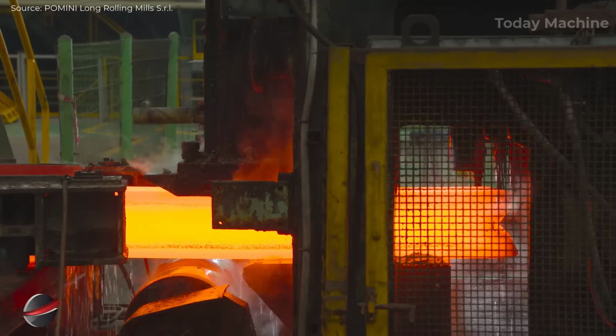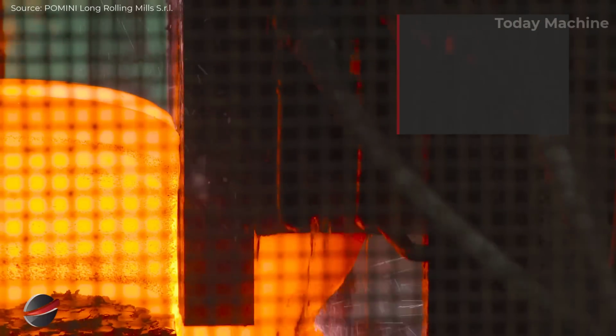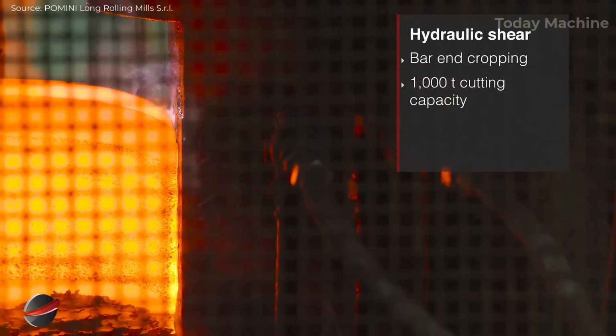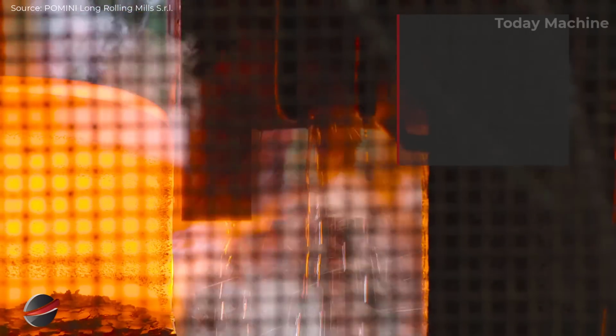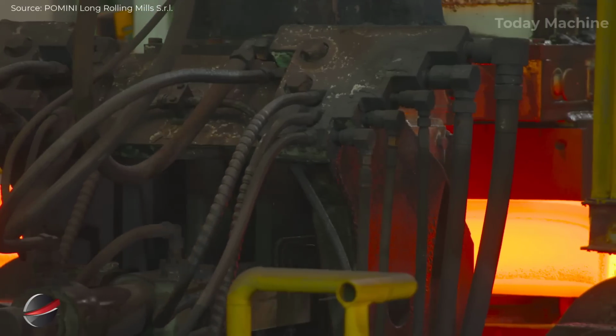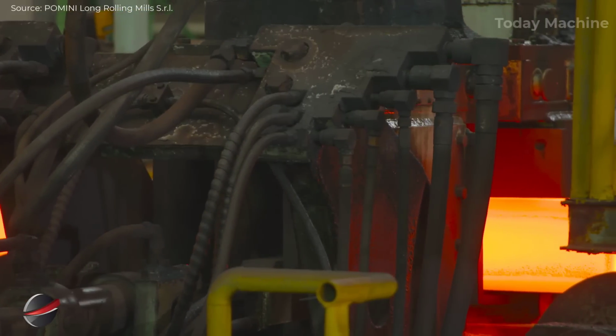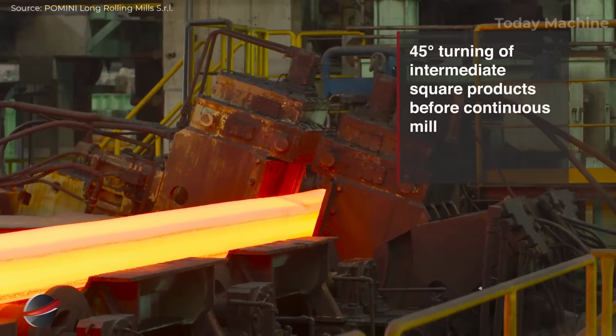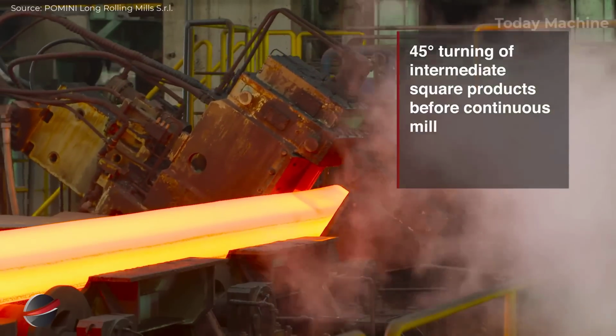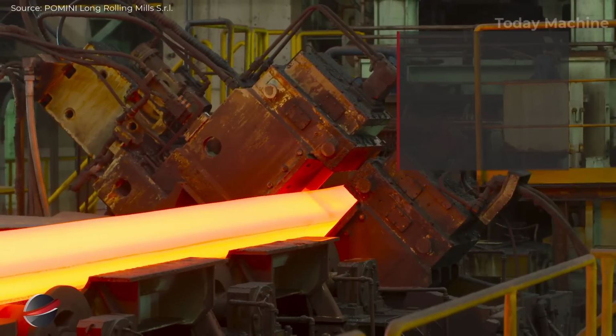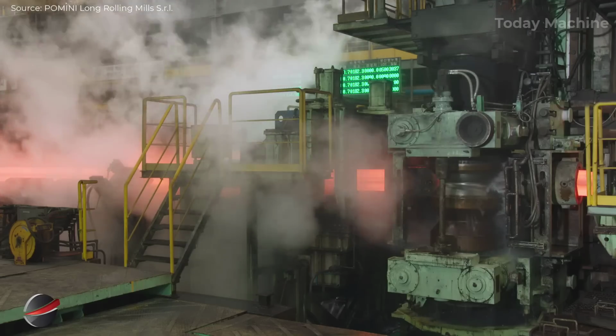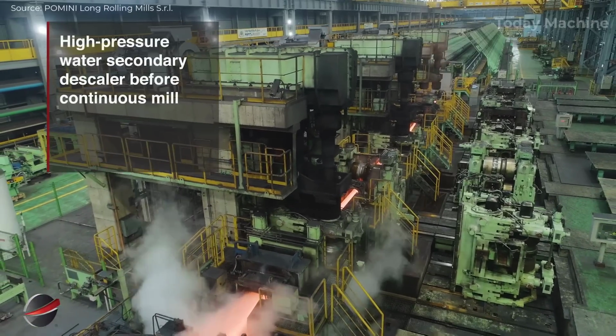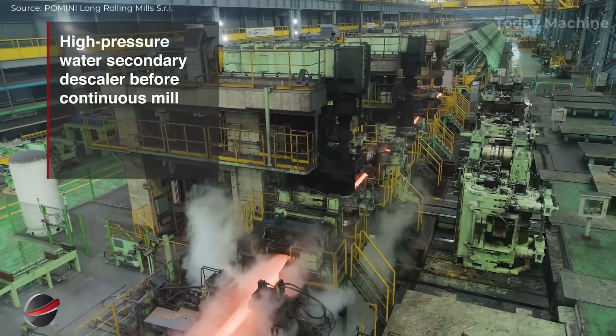The blooms are processed into intermediate square products, and hydraulic shears are used for bar end cropping with a cutting capacity of 1,000 tons. The intermediate square products are then rotated at a 45 degrees angle before proceeding to the continuous mill. Before entering the continuous mill, the intermediate products undergo another round of descaling.